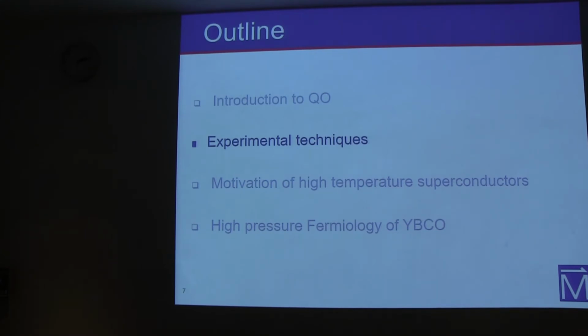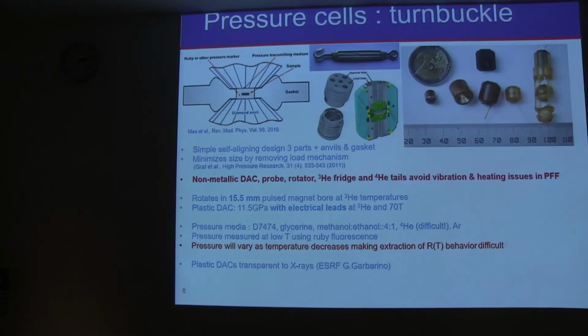So now, how do we make those measurements? I'll start with pressure cells. Pressure cells are typically very big, and the main criteria for diamond anvil cells, where you have two diamond anvils, is that for hydrostatic conditions, we need a pressure transmitting medium, most often a liquid, and the liquid is held in between the two anvils by a gasket.